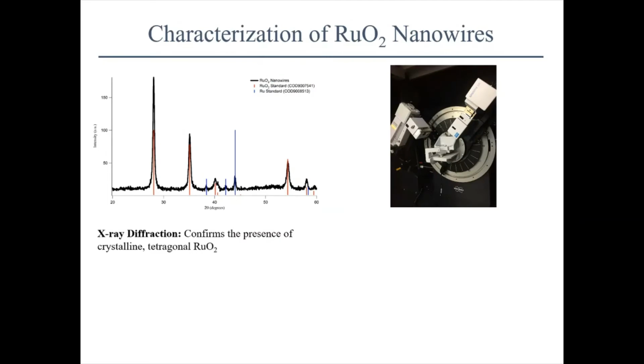So we have a standard set of characterization techniques we use at Fordham University. One is X-ray diffraction. When we took the crystalline product out and did X-ray diffraction, we saw that the material was primarily made of tetragonal ruthenium oxide, which are the peaks denoted by these red standards. We also saw a little bit of metallic ruthenium, which was probably at the core of the wire. We suspect that because to oxidize the gel, you need a source of atmospheric oxygen, oxygen from the air to react with the ruthenium to form ruthenium oxide. So it makes sense that at the surface we would get ruthenium oxide, and the core, which is isolated from the atmosphere, when annealed, may have led to the production of some ruthenium in the absence of oxygen from the atmosphere.